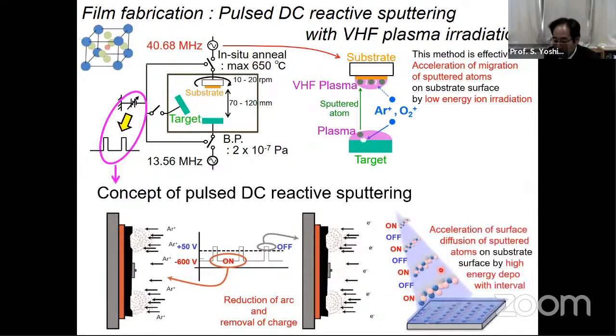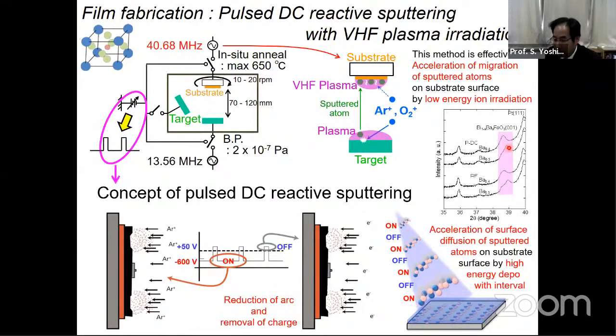And also, this system has many merits about the acceleration of the surface diffusion. So we can apply very large power to the sputtering target with interval time. This is very important for surface diffusion of sputtering atoms on the substrate surface. This is the result. The film fabricated by this system has high quality compared with the normal RF sputtering system.